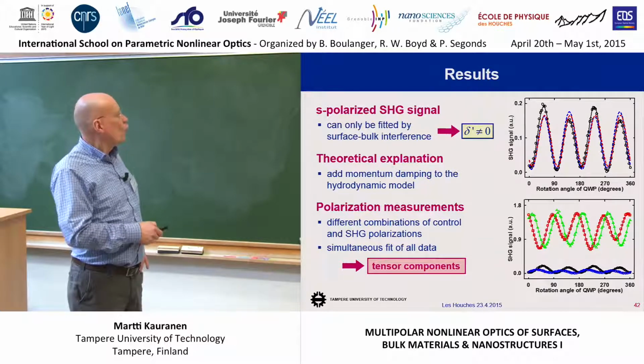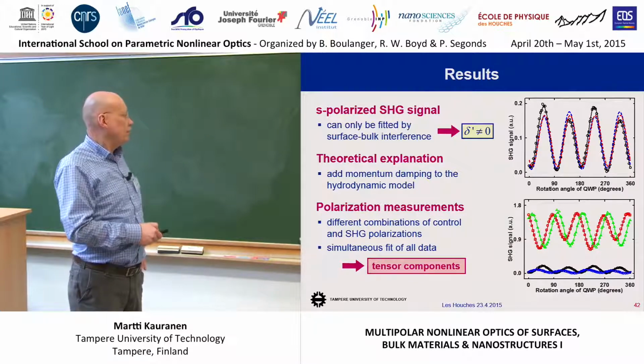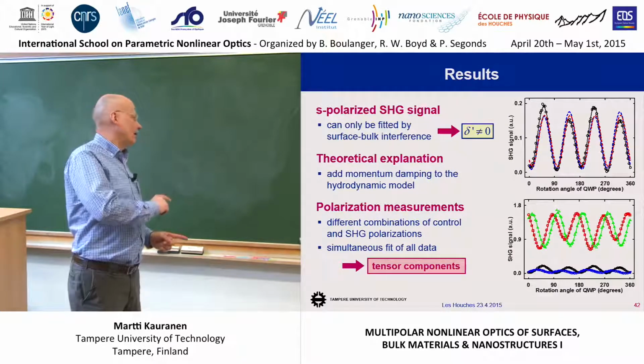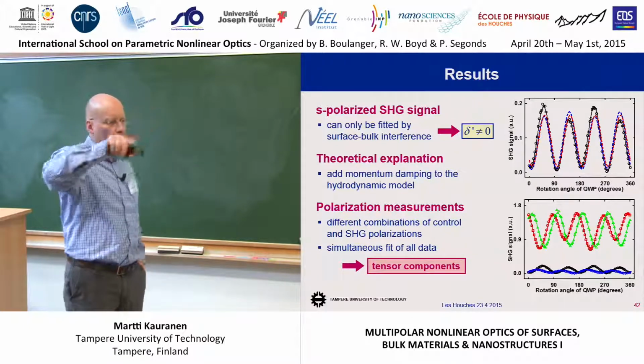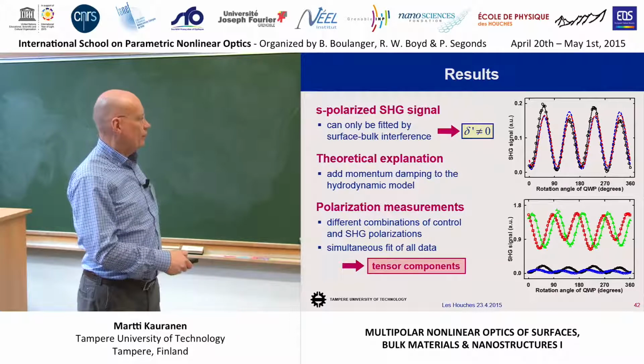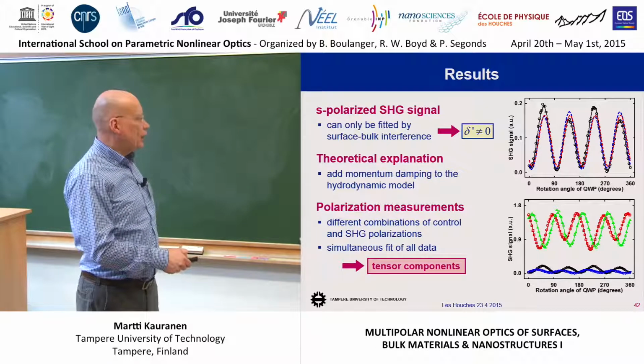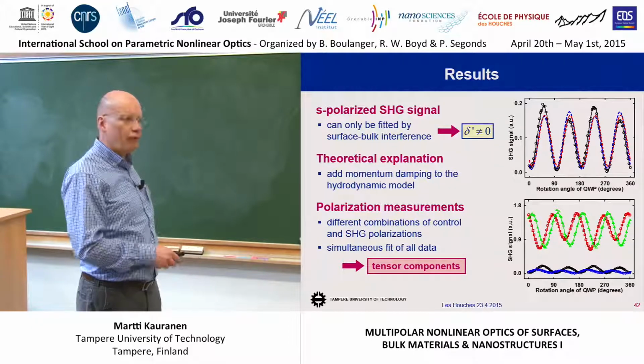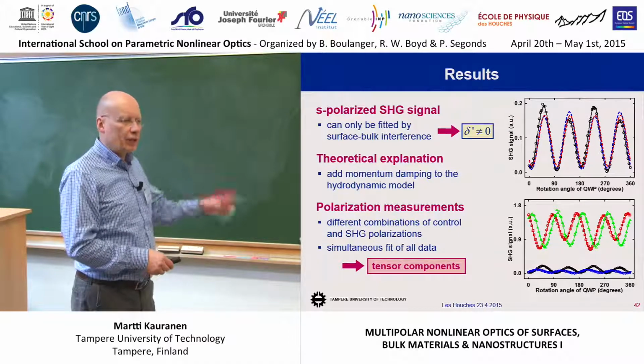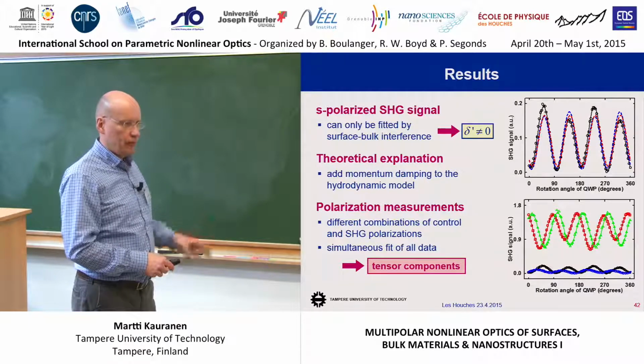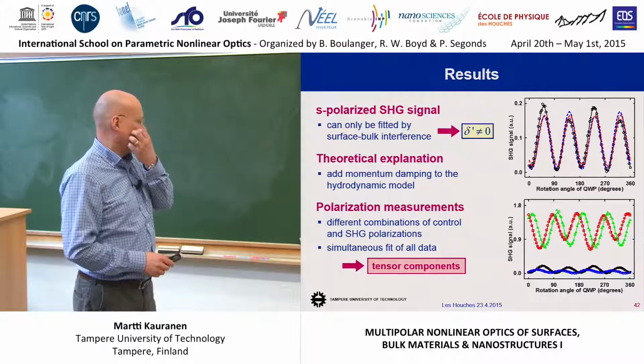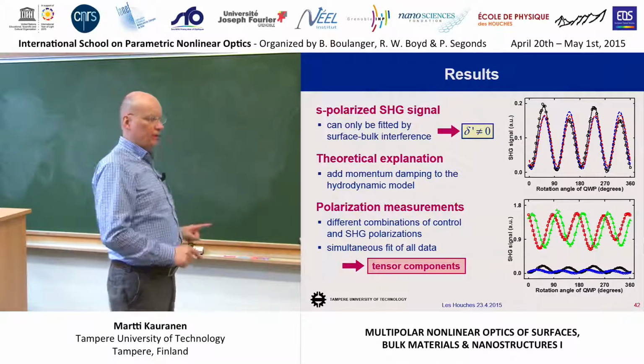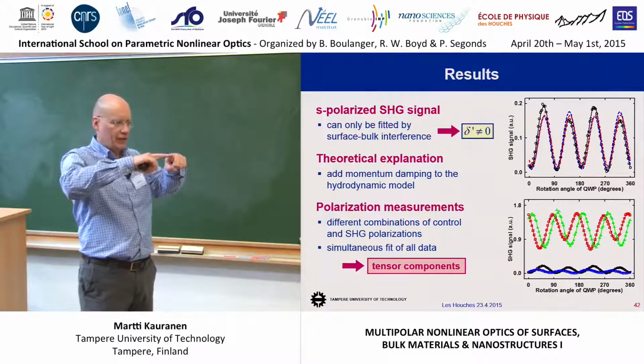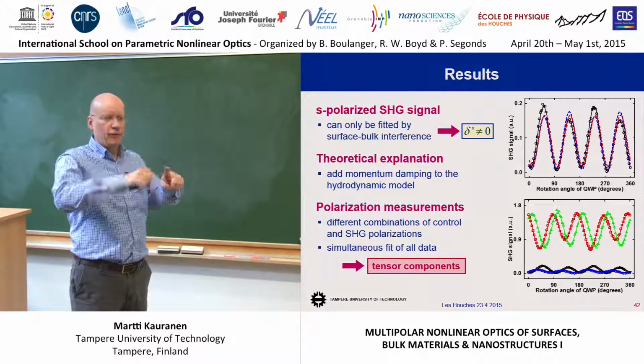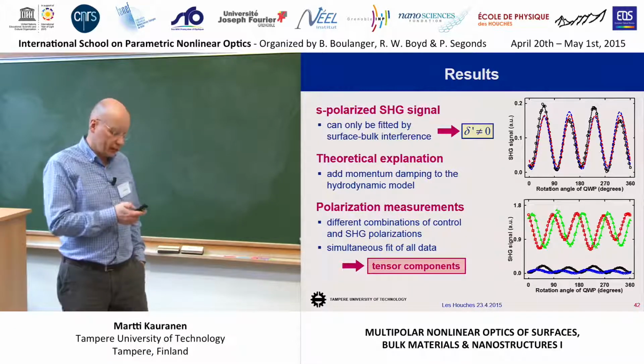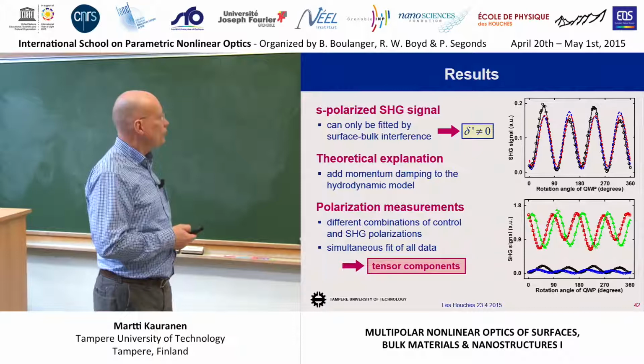Then we did this more complete set of polarization measurements using different combinations of control and second-harmonic polarization, modulating the probe polarization, and measuring 4 different sets of data, trying to fit this into this unique set of these F coefficients, and then solving the actual tensor components from the data. It's a lengthy but straightforward procedure. The main trouble is that you have to do the experiments really carefully, 2 beams in the same plane of incidence. Everything is very, very sensitive to any misalignments and things like that. But in the end, we got results,